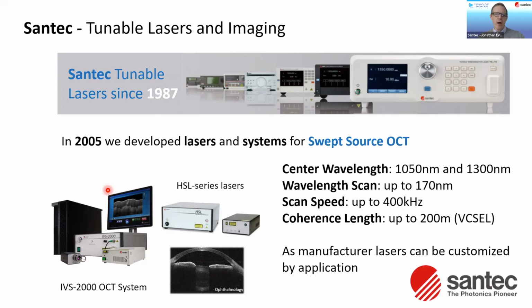And we have a range of lasers centered at 1 micron, 1.3, with wavelength scans up to 170 nanometers, scan speeds up to 400 kilohertz, coherence length up to 200 meters from the latest VCSEL lasers. And as a manufacturer of the laser, we can really customize these sources for different applications.